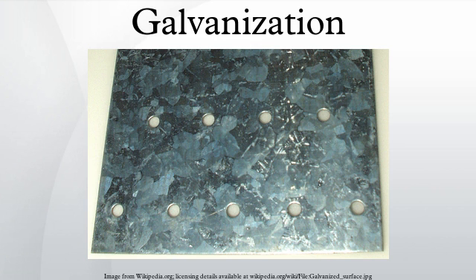The size of crystallites in galvanized coatings is a visible and aesthetic feature, known as spangle. By varying the number of particles added for heterogeneous nucleation and the rate of cooling in a hot-dip process, the spangle can be adjusted from an apparently uniform surface to grains several centimeters wide. Visible crystallites are rare in other engineering materials.